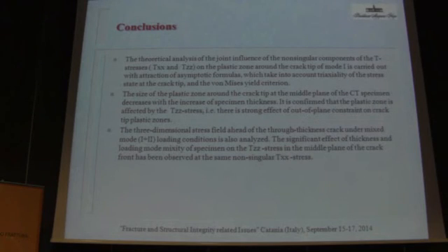And finally, conclusions. The theoretical analysis of the joint influence of non-singular components of the T-stresses on the plastic zone around the crack tip of mode 1 is carried out with the use of asymptotic formulas, which take into account the triaxiality of the stress state at the crack tip and the von Mises yield criterion. The size of plastic zones around the crack tip at the middle plane of the CT specimen decreases with increase of specimen thickness. It's confirmed that the plastic zone is affected by the out-of-plane constraint parameter. There is a strong effect of the out-of-plane constraint parameter on crack tip plastic zones.